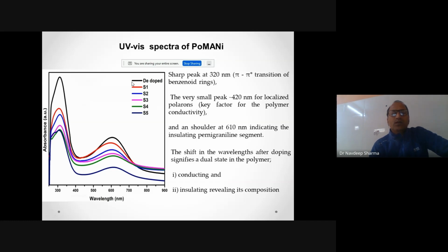And we have to check at which dopant concentration our conducting polymer shows better results. The UV-vis peak at 320 nanometers shows the pi-pi star transition for the benzenoid rings, and the very small peak at 420 nanometers is for localized polarons, which is the key factor for conductivity in the polymers. The shoulder at nearly 610 nanometers indicates the insulating pernigraniline segment,